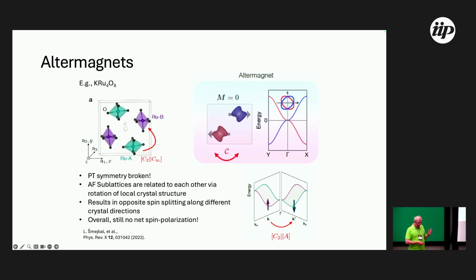But in an altermagnet, the situation is slightly different in that the local structural environment around the two sublattices is different. It has a different crystalline orientation. For example, in this material, potassium ruthenium oxide, you have these octahedra that are rotated 90 degrees with respect to each other. And so it's easy to think that the electrons associated with this sublattice move differently in this direction versus that direction, and for electrons sitting on this sublattice, the situation is 90-degree rotated. And so what you end up with is a spin splitting of your electronic band structure that's different in two different spatial directions.